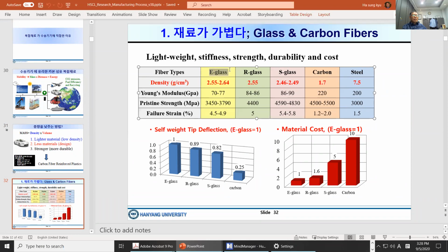Speaking of being light, let's consider many different fibers. E-glass, there are many different types of glass: E-glass, R-glass and S-glass, and even carbon fiber. By comparison, we have steel. Look at these values. E-glass has a density of 2.5. There are many different glasses, but average-wise, the density is about 2.5. That's a good number we need to remember. And carbon, the density is about 1.7, and steel, 7.5. Very heavy, about 5 times.